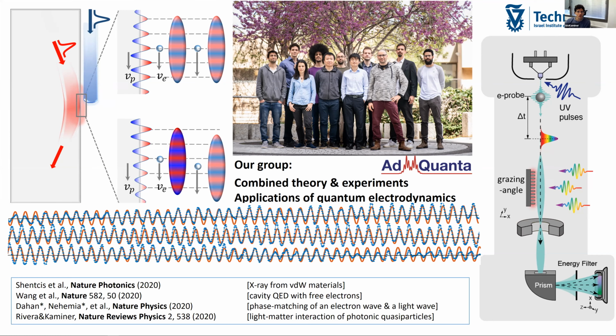What we do when we bring the laser in is that we stimulate the entire process. So we can make the peaks that we normally think about as very small, we have to subtract the zero loss peak, significantly larger, as big as the zero loss peak. And that makes it possible to observe EELS peaks in scenarios that are normally not observable, and it makes it much easier to do. So it stimulates EELS in a very efficient way. So samples that normally are not efficient enough for EELS will here be observable. We'll be able to identify those features. And that's one example that I think is a good highlight of what we can do.